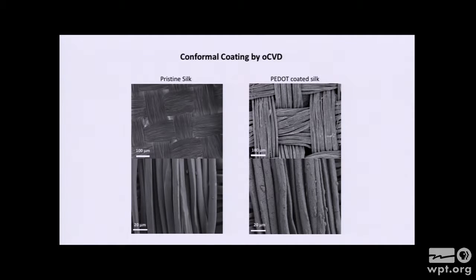But note the amazing level of control that we have, and we're really not even trying that hard. We have the PEDOT that coats the fiber, again, conformally, but even when we have the different woven pattern, we're not even coating individual threads and then weaving a pattern afterwards. We have our pre-woven fabric substrate, and the PEDOT, again, conformally coats all of those weave patterns as well. So we can effectively take a woven material and deposit PEDOT on it.